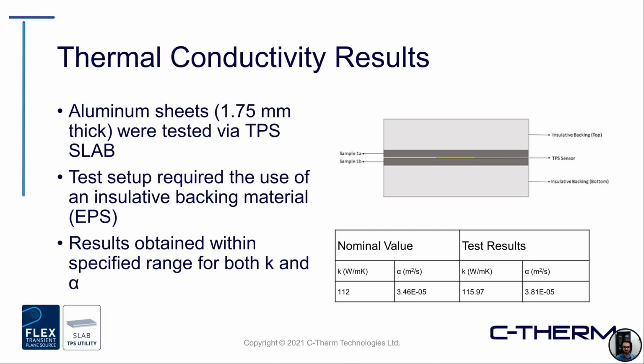It does require a slightly specialized test setup compared to your base TPS measurement. You actually have an insulative backing layer on the top and bottom of each sample. In this case, we're using EPS foam. But again, looking at some of the results that were obtained on this grade of aluminum compared to the reference value, conductivity and also diffusivity are well within what we would expect with our final measurements here.